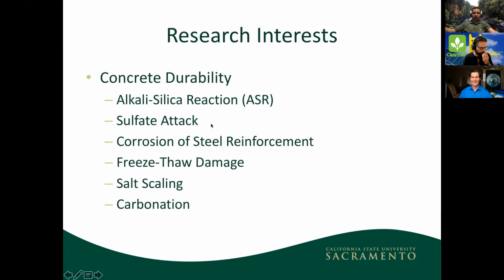The other very nice thing about having ended up in California is that, at least fortunately for me, there are a lot of durability issues. Where we live in California, there's a lot of alkali silica reaction, which attacks concrete from the inside. There's a lot of sulfate attack because our groundwater and our soils have a lot of sulfates. When they penetrate concrete, they start attacking it. They start kind of eating it away. And I have some pictures here on the next slide, but these are very, very common in California.